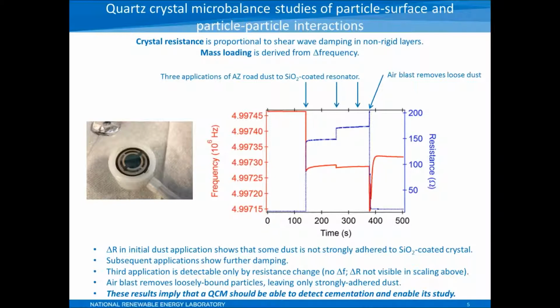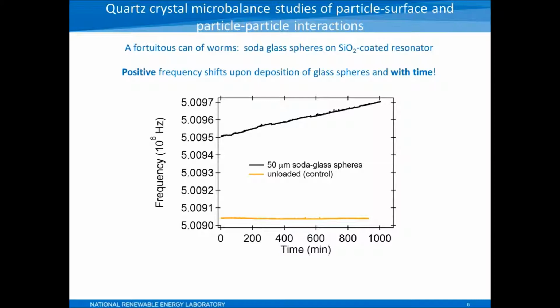Our analytical microscopy group, who I think have presented to this group before, have been doing a number of AFM experiments, trying to quantitatively understand things like capillary forces and van der Waals forces. In those experiments, the probes are SiO2 spheres of about 20 microns. So I obtained some of these spheres. In this case, they're 50 microns, and I did the same sort of application to the resonator and immediately opened up a can of worms. I modify that with the word fortuitous because although it did initially baffle me, we ended up learning quite a bit about the interactions of particles and quartz crystal resonators.